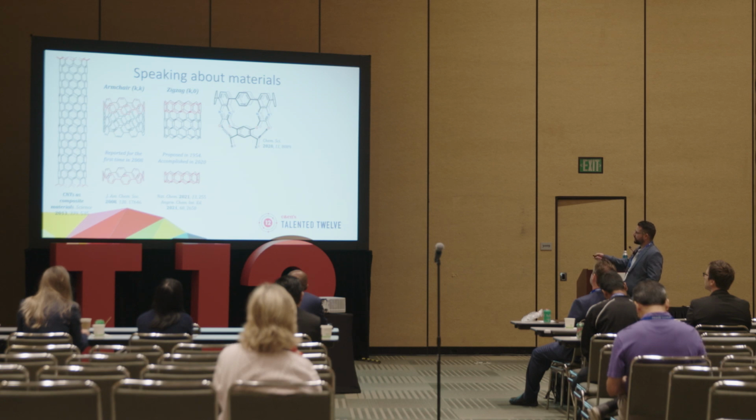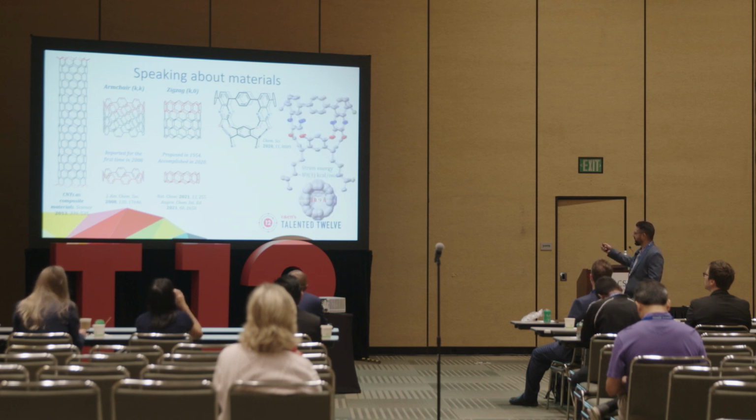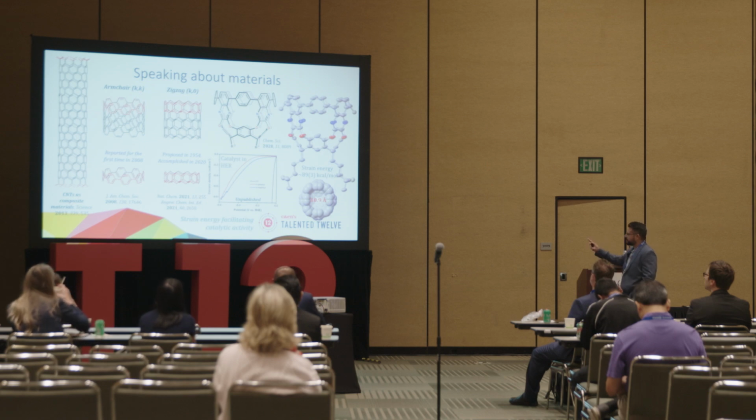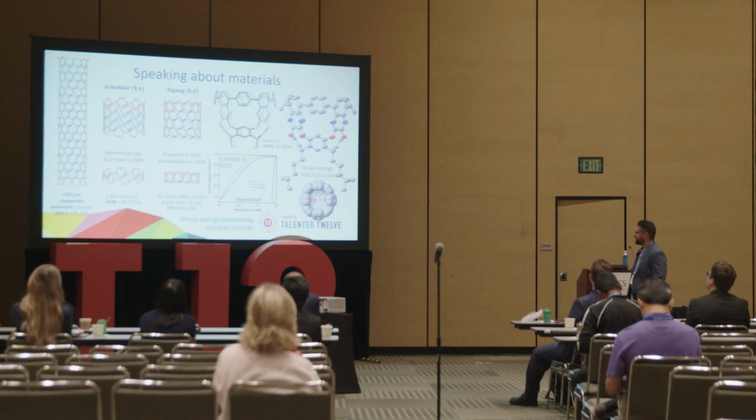In my group, what we've done is taken this inspiration to create contorted nanotubes that we've synthesized, developed the synthesis for, characterized, and more recently, this is still unpublished, pushed into the area of catalysis. What we've learned with this type of materials is that the inherent strain that we're putting into these nanotubes, about 89 kcal per mole in this particular compound, we can start using to evolve dihydrogen, a very important transformation that a lot of people are researching through other materials.